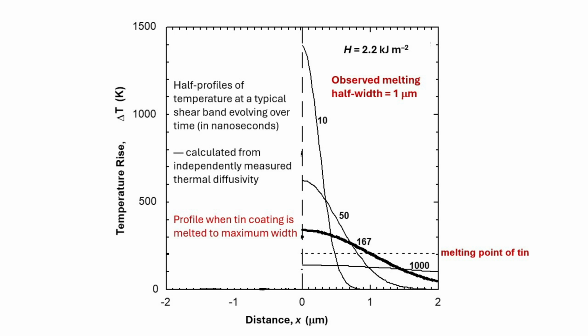So this is where the shear band is. Remember that in relation to microns, it's only nanometers. So out here, the coating never reaches the melting point of tin, and here it exceeds it. So this we would think is where it gets to as a limit. You can put some numbers into this.